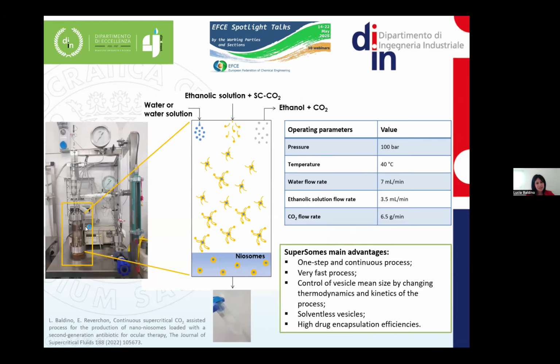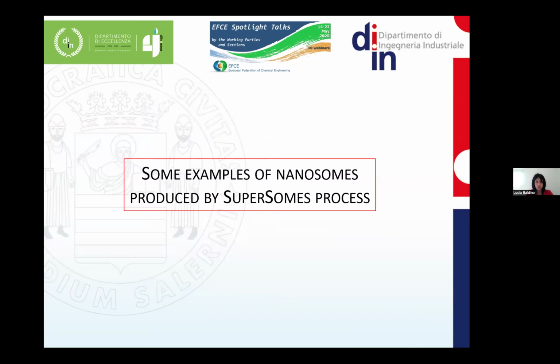Here I reported a sort of detail of what happens inside a pressure vessel. In the table, the operating parameters that we generally use for nanosome production. These parameters, pressure, temperature, and liquid flow rates, have been optimized in several previous works of the research group. So, summarizing, the main advantages of the Supersome process are: one-step continuous process, very fast process, control of vesicle mean size by changing thermodynamics and kinetics of the process, solventless vesicles, and high drug encapsulation efficiency.